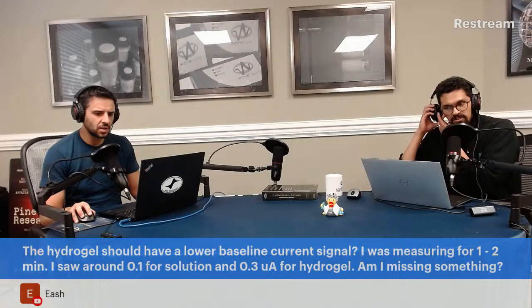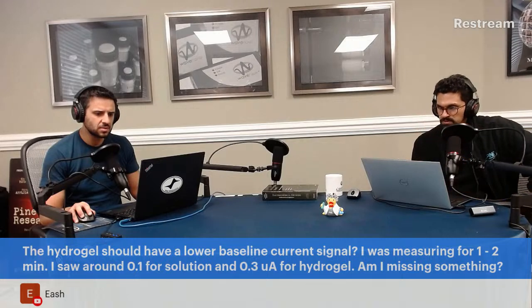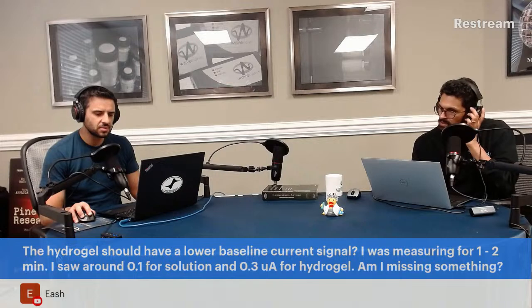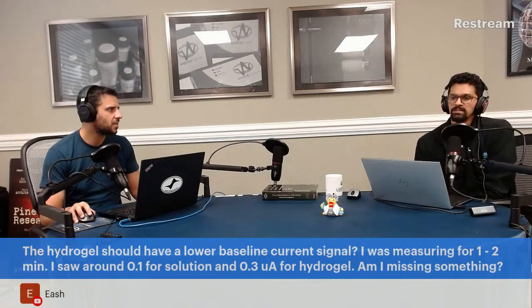Yash is following up here. Yes, the hydrogel should have a lower signal. Baseline current signal. I was measuring for 1 to 2 minutes. I saw around 0.1 for solution. So higher for the hydrogel. Higher for the hydrogel. It's actually backwards of what I think. Did we look at it right?